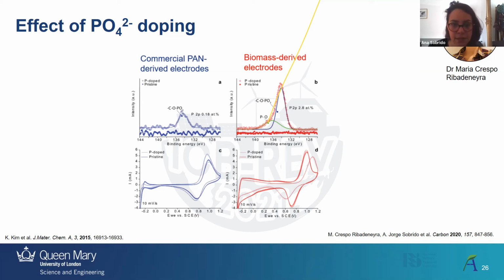But anyway, here what we see is a CV taken in a three-electrode electrochemical cell. As I said, the effect on the commercial one is positive, although quite low, probably because of a low doping. Whereas in our case, this one is the pristine. It performs much better than the lighter one, which is the phosphorus-doped. So it seems like in our case, because we already have quite an active surface, the addition of a phosphate, which is quite a big group compared to just the oxygen, might actually block access to other groups that are already there.